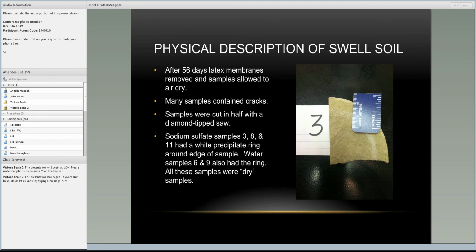What we found, at least with the SWELL samples, was that it was easier to find ettringite not by taking a heavy amount of the white precipitate, but by sampling near it, or actually even going to the middle of the SWELL sample and just getting parts of the soil that looked very brown with no white precipitate. We were more successful in finding ettringite in those areas.